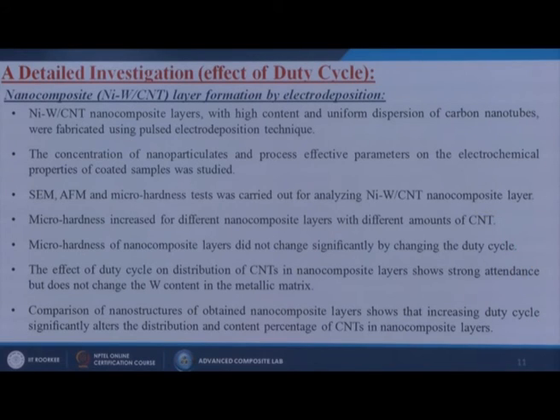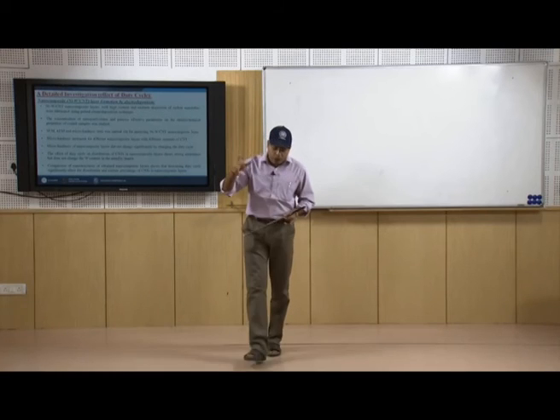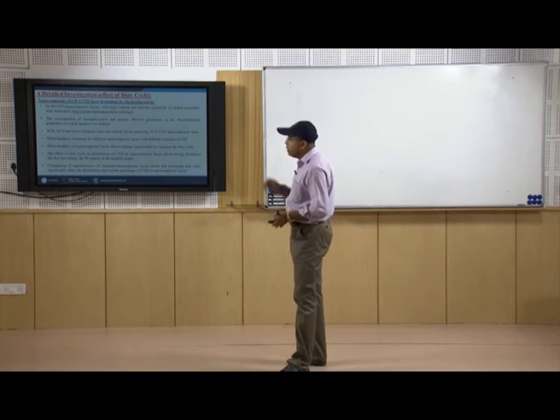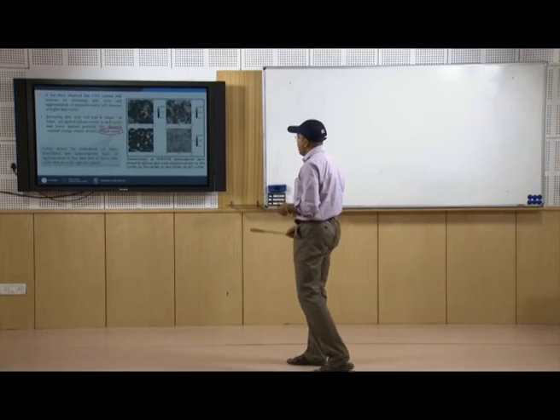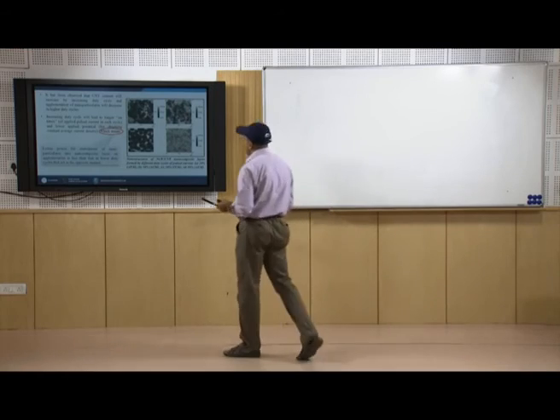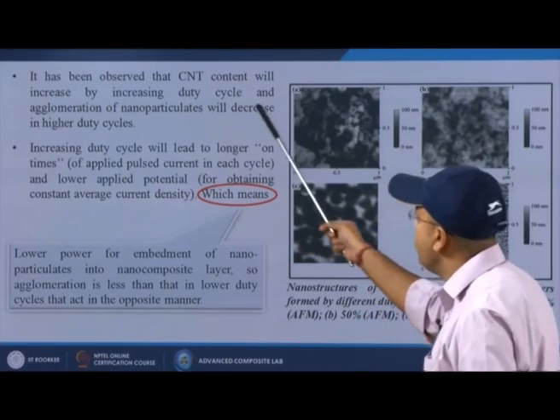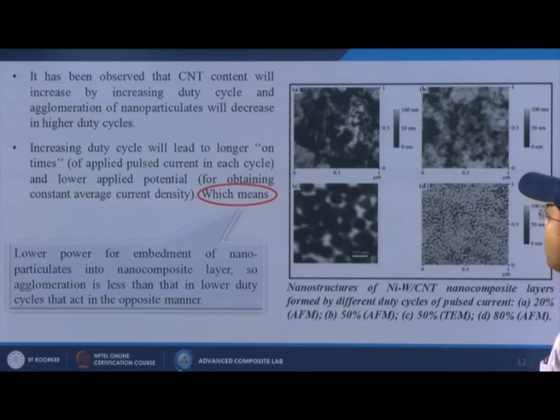Comparison of the nanostructures of the obtained nanocomposite layers shows that increasing duty cycle significantly alters the distribution and content percentage of CNTs in the nanocomposite layers. So these are all the results we obtained by doing this kind of testing, or by making this kind of material. Here we are trying to show you some results. It has been observed that carbon nanotube content will increase with increasing duty cycle, and agglomeration of nanoparticles will decrease at higher duty cycle. So that is the added advantage in this particular case.